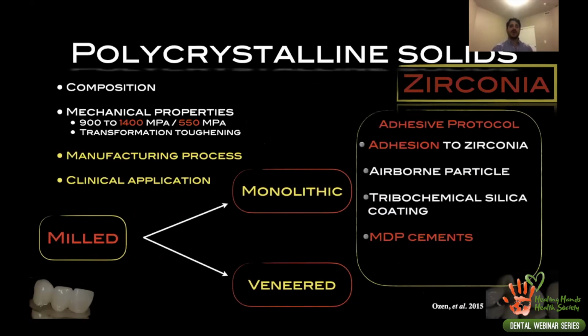The adhesive protocol to the zirconia, since we don't have a glass phase, is somewhat controversial as well. It is proven in the literature that you can achieve a good bonding to the zirconia by applying air abrasion to the intaglio, or the internal aspect of the crown, with the use of an MDP cement, or a cement that has MDP within it. And that can achieve a good and predictable bonding to the zirconia.